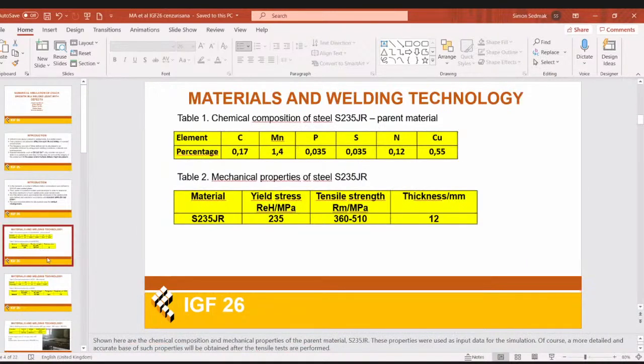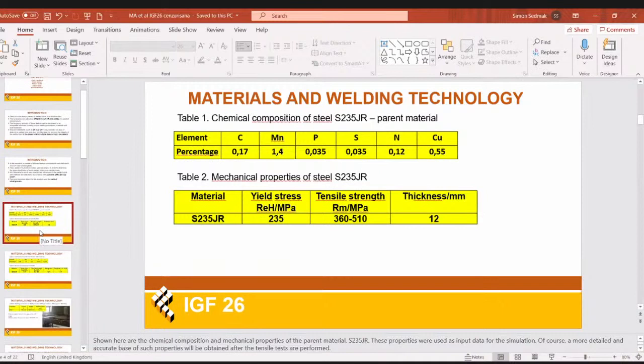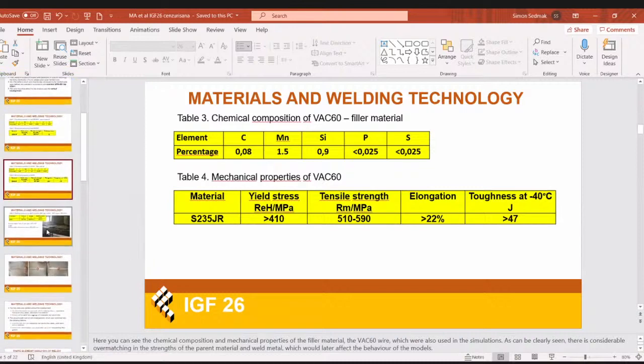And for this purpose, we welded some plates using typical structural steel, and then decided to make some numerical simulations of different cases, while at the same time performing various experiments so we could validate this approach and see what we can basically expect depending on different combinations of defects, which generally included misalignments, excessive weld metal, undercuts, incomplete root penetration, and anything else that tends to appear frequently during the practice.